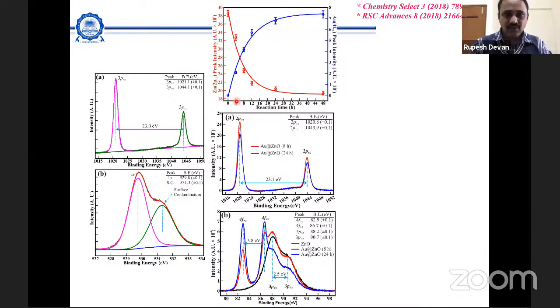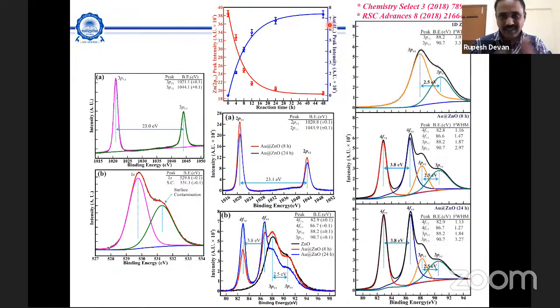And you can see here, as soon as we increase the reaction time, the gold quantity is increasing and it reaches the supersaturation state, or you can say the saturation state, after 24 hours. Even if you increase the reaction time, these gold nanoparticles were agglomerating. So we can see the information about this. These gold nanoparticles have been observed here in pure form, and the zinc oxide is there.